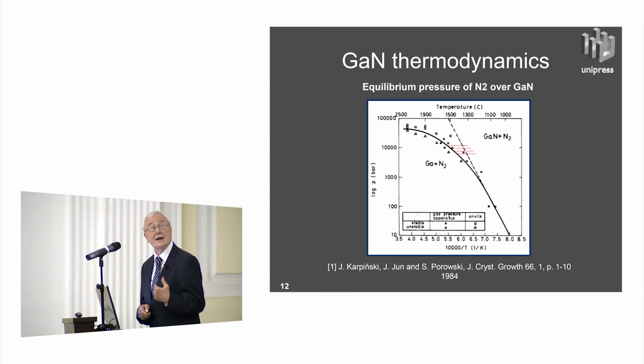And at this time we also knew that there is a region here, marked with these red lines, at which we can grow single crystals of gallium nitride from a solution of nitrogen in gallium. And at this time, the high pressure technique in the institute was developed to the point that we knew that such a process is quite feasible. So at the time when the first diodes were produced, we started very intense work on the development of single crystals of GaN and also substrates from GaN.